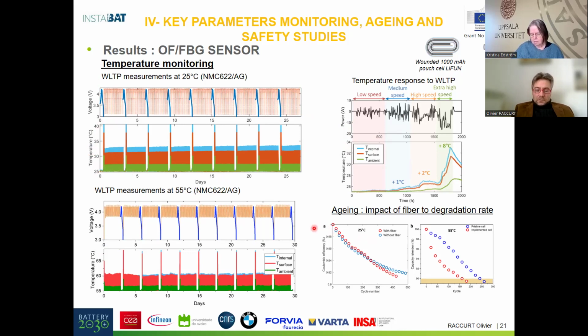And you can see in this graph the internal and external temperature of the cell. We observe that the degradation of the cell is very similar for the cell with and without the sensor inside. But after more than 350 cycles, there is a slight difference when we test the cell at 25 degrees. But at 55 degrees, there is a huge effect of the presence of the sensor on the degradation, because the cell with the optical fiber decreases very quickly in terms of capacity during aging.